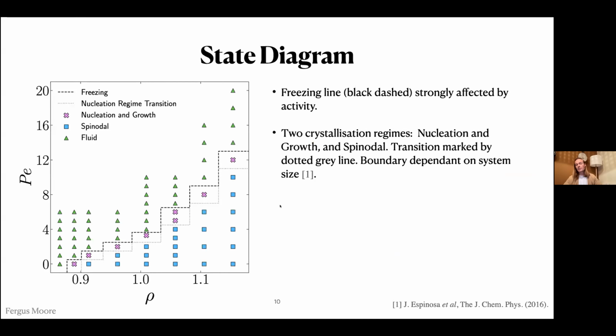So here's a state diagram, which is a bit of a map of the area that we're looking at today. So we're varying the total density on the x-axis, and then for each one of these densities, we change the Peclet number and look at the structure of these states. So we have a freezing line here. Everything to the right of this black dashed line is crystalline. And then within there, we define two different types of nucleation mechanisms within which these crystals grow. And I'll be getting into those two different mechanisms shortly.